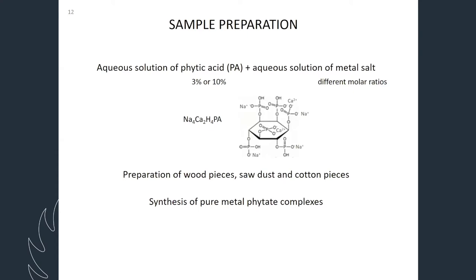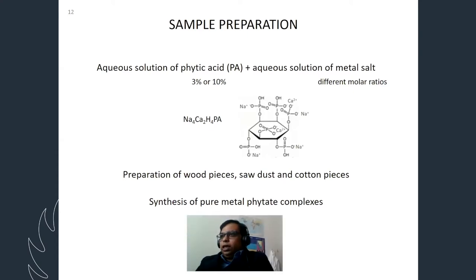So I can take over now, and I will discuss the experimental part of the project. We prepared the phytic acid solution first, from commercially available phytic acid, which you can find from most chemical producers, and it comes as a 50% aqueous solution. From there, we diluted to 3% solution and 10% solution. And that's our standard we used for our trials.